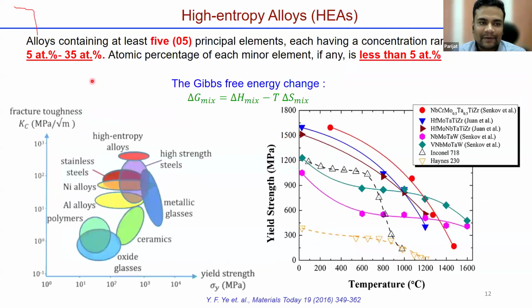Now you see, as per the definition, it has at least 5 principal elements. You need at least 5 so that the mixing entropy will be sufficiently high to stabilize simple solid solution phases. And if you see its fracture toughness and strength as a function of temperature, compared to superalloys and other alloys, the high entropy alloy's fracture toughness is very high. Stainless steel, nickel alloy, polymer, metallic glass, all these are below, and high entropy alloy sits at the top. Similarly, as a function of temperature, they also show very high strength retention.